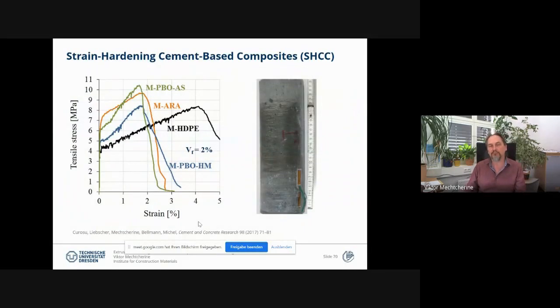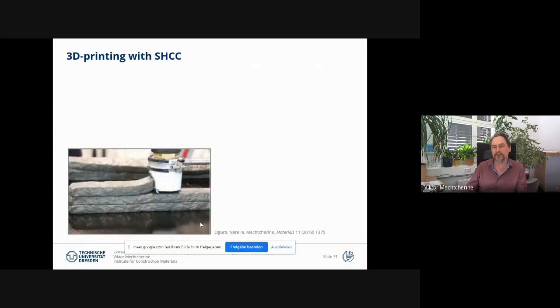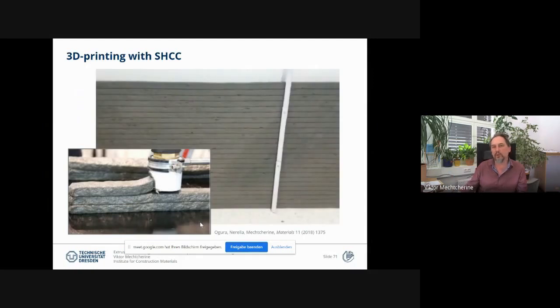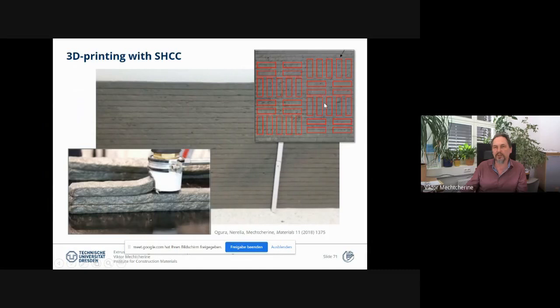Well, again, a pretty straightforward approach is to put some fiber in the print material. Fortunately, we have nowadays fiber reinforced concrete which is of very high performance. As this example shows, we have a strain hardening behavior of the material by additional fiber of about 2%. And we tested this and published about 2 years ago. So you see here that SHCC as a strain hardening cement-based material can be printed. We produced, again, walls of different sizes.